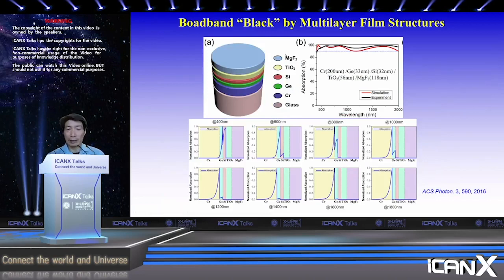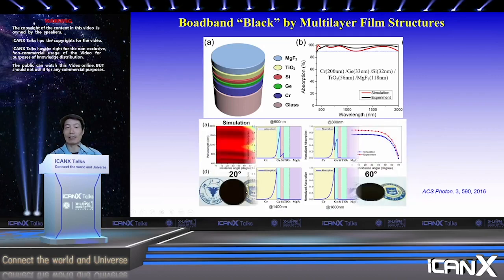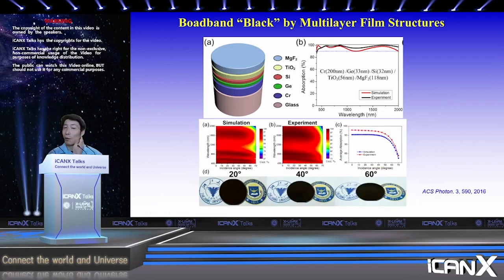It consists of multiple materials, but the idea is that it creates multiple optical resonances. Certain materials are responsible for absorption at certain wavelengths, as indicated in the bottom panel. The overlap of these resonances gives rise to broadband absorption. So you can see that the sample looks very black. In fact, I think in the visible wavelengths, it absorbs 99% of the light using a very simple layer structure.